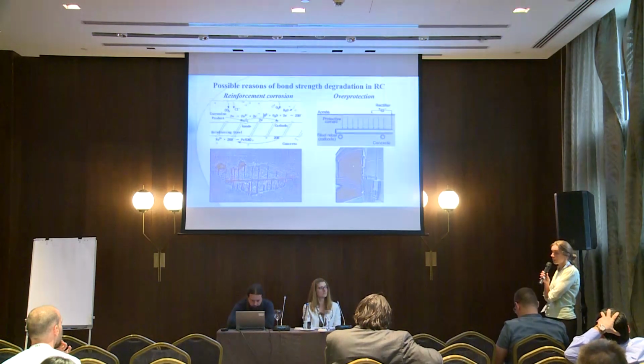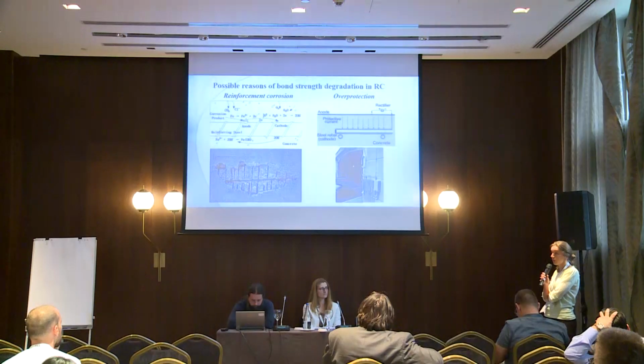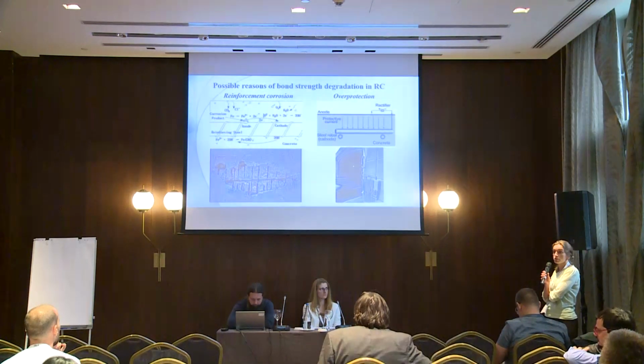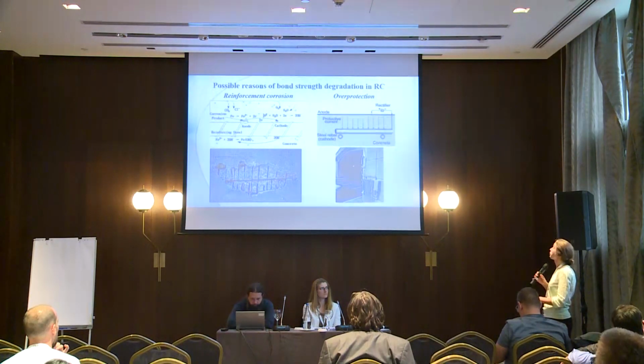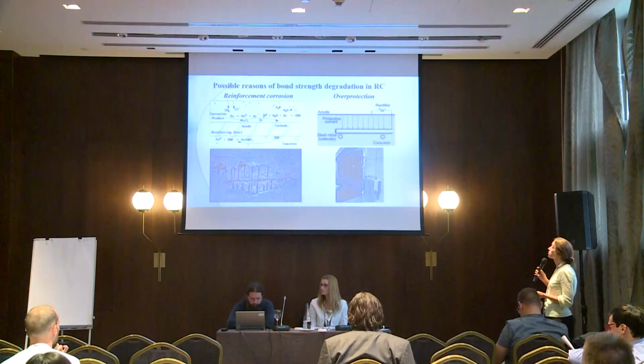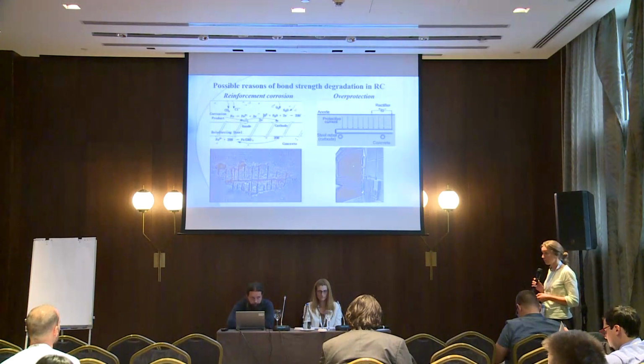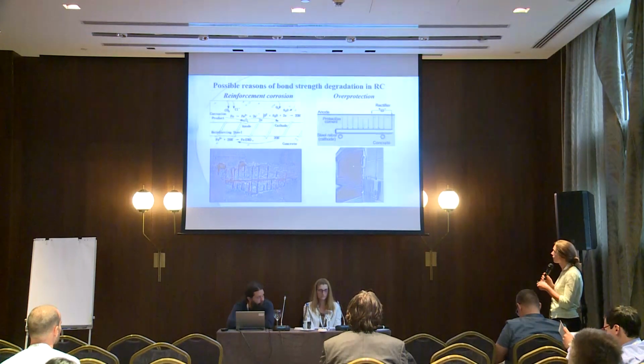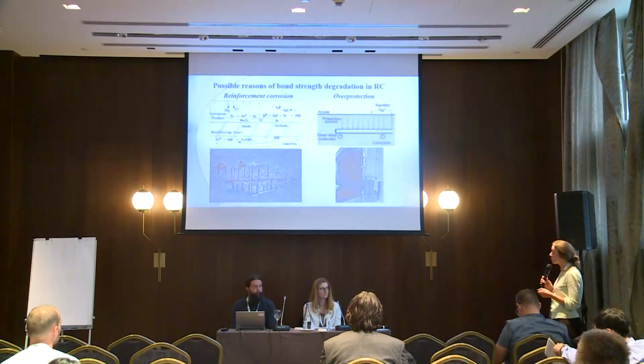However, it is well known that only a tiny part of hydrogen electrochemically generated on the steel surface can penetrate the metal, and most of the hydrogen recombines and evolves as a gas at the steel surface surrounded by concrete. And it seems to be important to analyze the role of just this hydrogen on the steel concrete interface and on concrete itself as well. Both mentioned effects which could cause bond degradation in reinforced concrete could be simulated in laboratory conditions by respective electrochemical methods, namely application of impressed anodic currents to accelerate corrosion, and cathodic polarization can simulate overprotection of concrete.